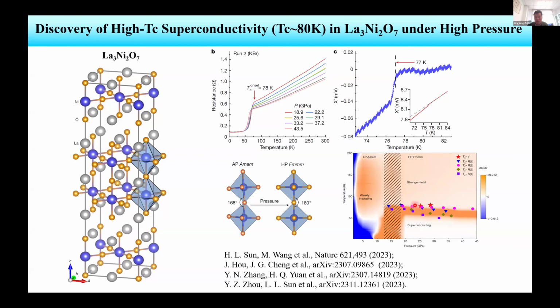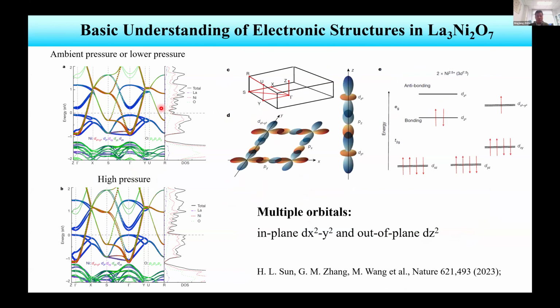Okay, this is the phase diagram they observed. Of course, it's very important to understand the electronic structure in order to understand the origin of the superconductivity. Band structure calculations indicated that near the Fermi level, the electron states mainly come from the in-plane nickel dx2-y2 orbital and also the out-of-plane dz2 orbital. The in-plane dx2-y2 orbital and the out-of-plane dz2 orbitals are connected by oxygen. These are the basic electronic structure of the La3Ni2O7.